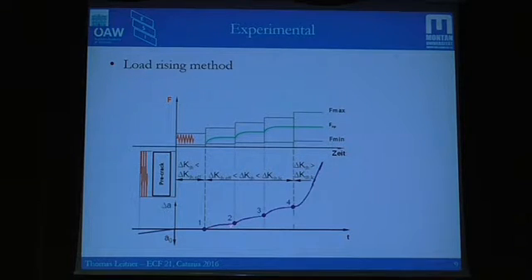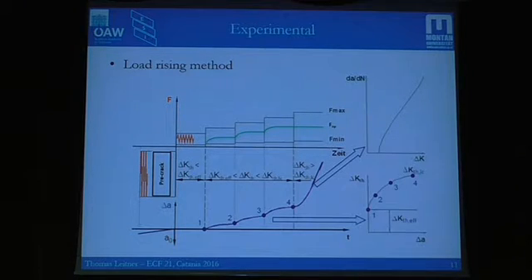The crack can then stop, and we need to further increase our delta K to get further crack extension. We do this again and again until we reach this point here, which is the long crack threshold, usually also measured in the load shedding method. From just this last part, we get our fatigue crack growth curve, as in the load shedding process. However, we can also get very interesting information about this part here with our load rising method, the cyclic R curve behavior shown here.